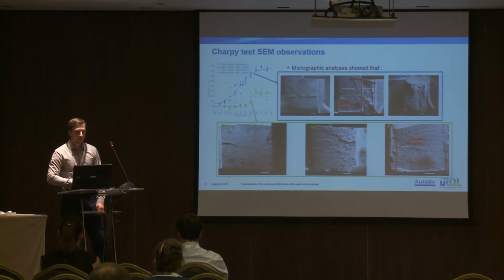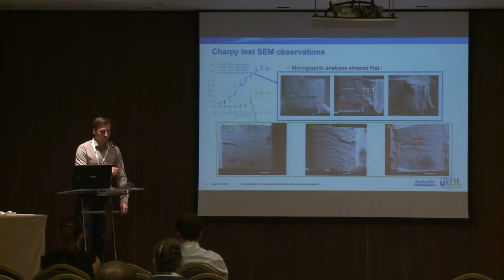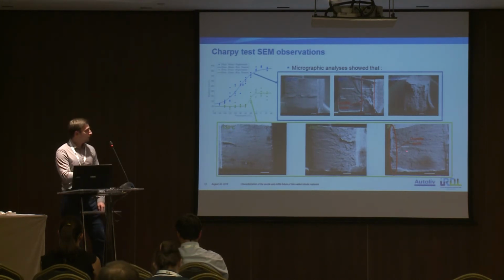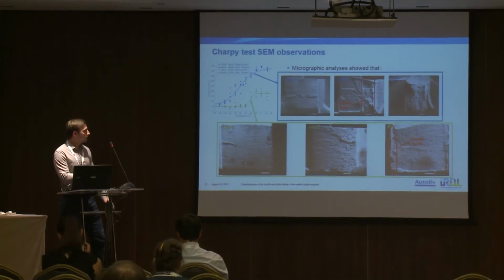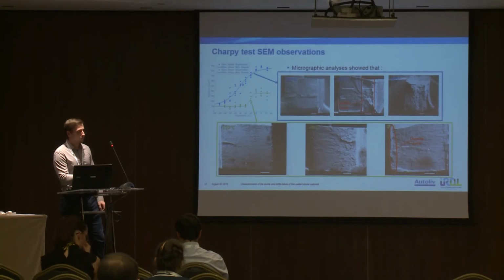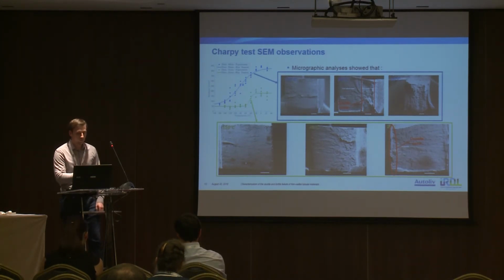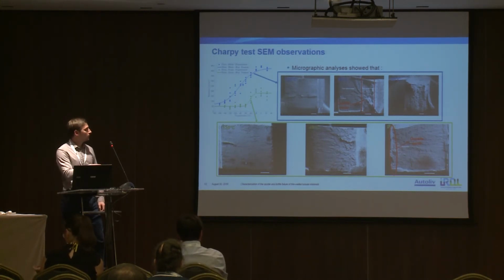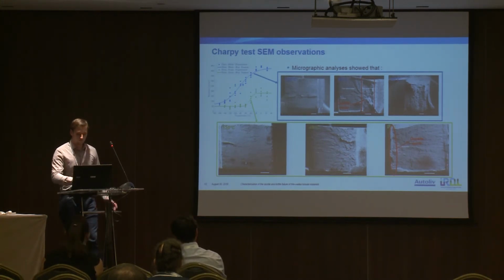So here there is an interesting result, because when we have exactly the same initial material and we apply a large pre-strain field to the samples, the behavior totally changes. So we have to explain and explore these effects in my study.